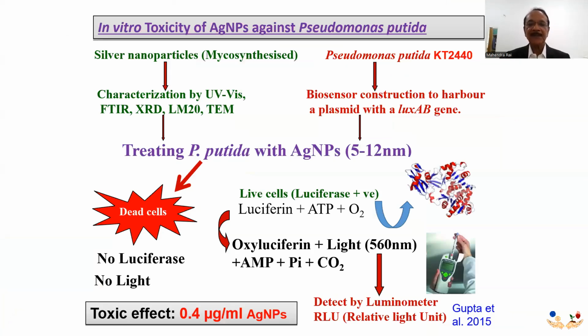Another experiment we did with Ann Anderson of University of Utah of United States. We selected Pseudomonas putida, a very good bacterium. It is a rhizosphere bacterium. And we developed the biosensors with the help of the luxAB gene. And when these bacteria were treated with 5 to 12 nanometer size silver nanoparticles at concentration 0.4 microgram per ml, they died. And we tested it in the biosensor.